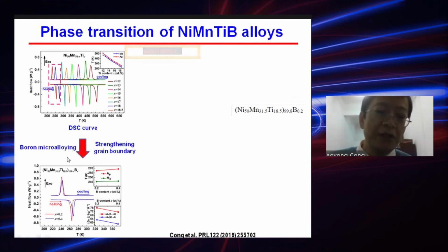As I just mentioned, the nickel-manganese-titanium alloy system has the best intrinsic mechanical properties. But for the polycrystals, especially for the alloys with large volume change across phase transition, the grain boundaries are very weak. Therefore, we use boron microalloying to strengthen the grain boundary in this alloy system, so that we can expect good mechanical properties in the polycrystals.